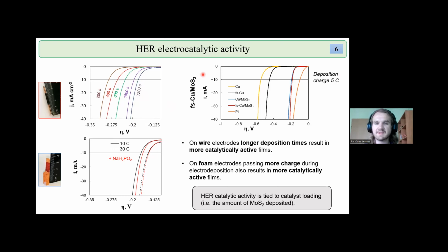Now, on a femtosecond laser ablated surface, we only examined a single charge, which is 5 coulombs, as the amount of material deposited. Even then, we can see that the material is fairly electrocatalytically active, and even more so than a comparable film that had been deposited on a non-laser ablated surface.